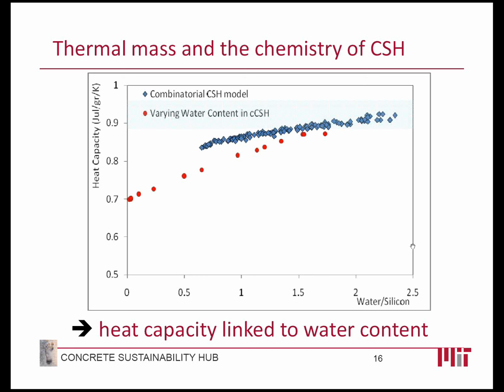Now that we know about the CSH granular system, we can calculate the thermal mass as a function of the chemistry of CSH. In this plot you have the heat capacity as a function of the water to silicon ratio, the W over S ratio. These are data from simulations exploring the chemistry of CSH, and we found out that the heat capacity is linked to the water to silicon content. You can see there is not much variation, within about 10% of heat capacity as a function of the water content.